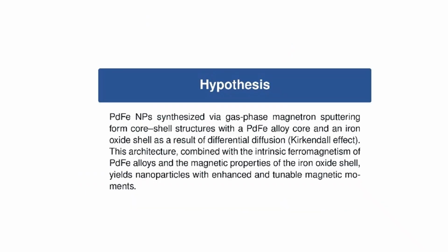Our hypothesis is that palladium iron nanoparticles synthesized via gas-phase magnetron sputtering form core shell structures consisting of a palladium iron alloy core and an iron oxide shell. This can occur due to differential diffusion, also known as the Kirkendall effect. We expect that this architecture, together with the intrinsic ferromagnetism of palladium iron alloys and the magnetic properties of the iron oxide shell, will produce nanoparticles with enhanced and tunable magnetic moments.